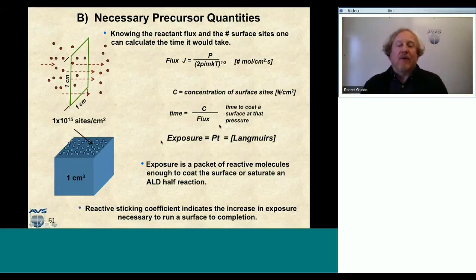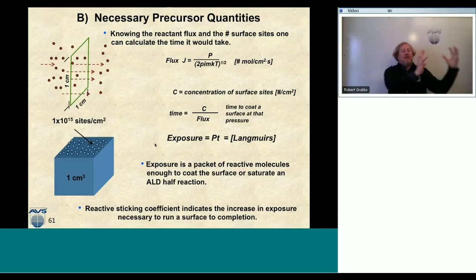And so now we're back to that's the time it takes. And if I take that time and multiply it by a certain pressure, then I get the exposure that I need in order to coat a given substrate. Now, if you want to think about exposure, if I have a flow tube, exposure is just this packet of reactive molecules. It's enough just to go through the reactor and coat all those surfaces or saturate the ALD half reaction. Now, this is not including the reactive sticking coefficient. So if I include the reactive sticking coefficient, which I have to because it's an ALD chemical process, then that indicates that I have to increase the exposure necessary to run those surface reactions to completion.